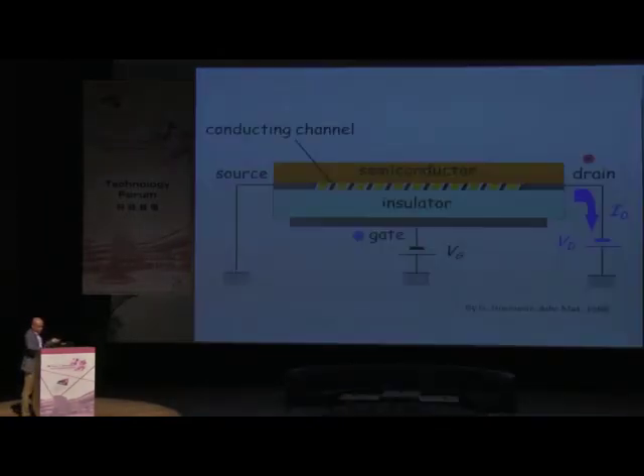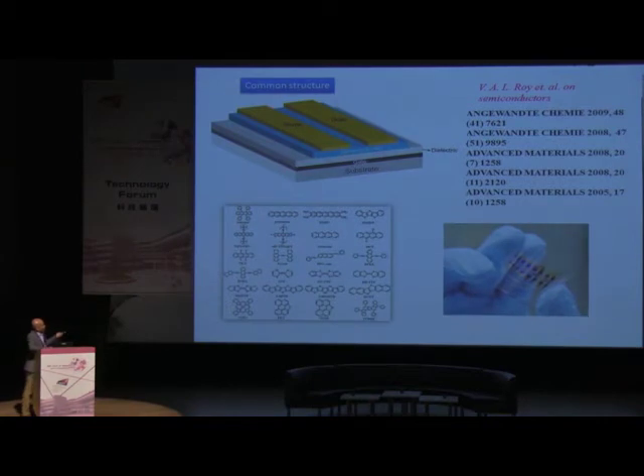In fact, I did a lot of work on the semiconductor part. I've been working on it since 2005, almost 9 years. We published a lot of papers on organic semiconductors and how to deposit them. This is a ring oscillator that works with a frequency of some hundreds of kilohertz that we made. When you make a semiconductor, you put it on a dielectric layer, and the semiconductor can be a molecular material, but when you put it on an oxide, you always have an interface problem. This interface is full of traps. How we are going to overcome the traps is one of the important things.